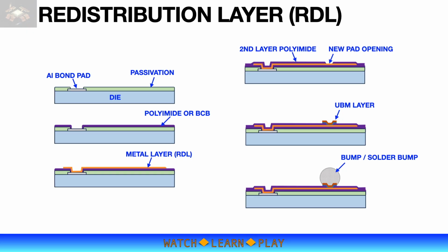The RDL process involves adding 1 or 2 layers of metal and 2 or 3 layers of dielectric material, such as polyimide or BCB. The polyimide layer is added on top of the existing wafer passivation, and a layer of metal trace is added to reroute the bond pads. Another layer of polyimide is added to protect the metal trace, but also exposing the new pads for bumping process.